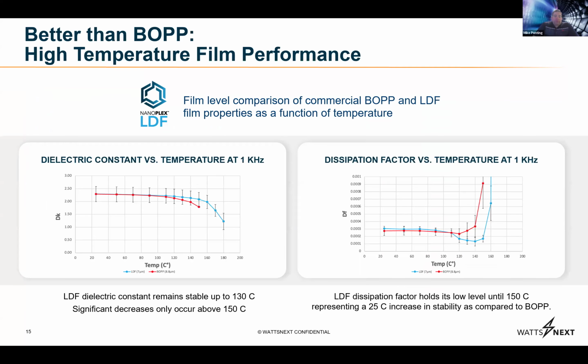So again, for LDF, I wanted to dig a little bit into some of the temperature performance that I was talking about there. The table's a nice summary, but if you get into some of the dielectric versus temperature data, which is showing here on the left, the dielectric constant as you increase the temperature or the environment that the material is operating at, our LDF, which is the blue line, is much, much more stable as compared to the commercial BOPP, which is the red line in there. So BOPP commercially, if you get to around 80, it starts to veer and you start to lose some of your dielectric storage capability, which will cause your capacitor to get derated.